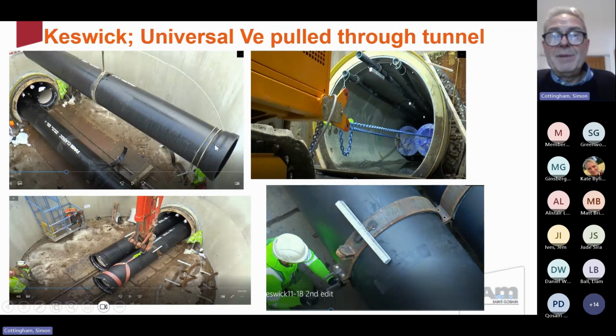In this application, again, the flexibility of the joint is a real benefit because there are tunnels with radius and curve, and the joint can cope with it, but there are also uneven tunnels. So we sometimes see in these applications double flange pipes proposed to pull through, which is not a great idea, because if there's any unevenness of tunnel, flange pipes have to span unsupported, which they can do, but you are going to stress the flanges and bolts. Not to mention flange joints don't have an indefinite lifespan, whereas the socket spigot joint gives you a 100-year plus design lifespan. So if you see anybody proposing to put flange pipes in tunnels, I would strongly recommend against it and recommend using the socket spigot universal VE joint for that application.